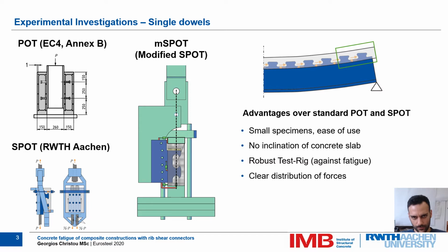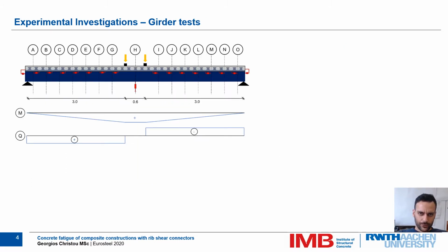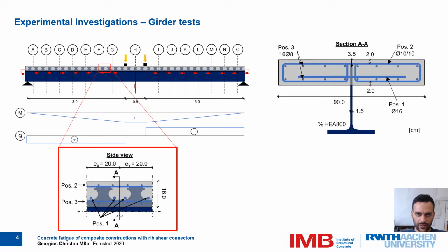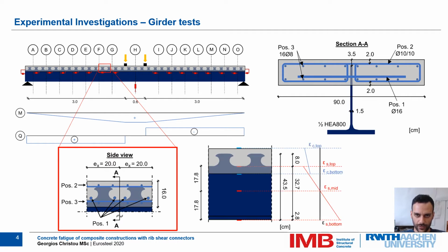Further advantages of the new modified single push-out tests are that our concrete slabs were relatively small and thus we had an ease of use. We had no inclination of the concrete slab as measured by the displacement transmitters, and we have a clear distribution of forces. In addition to the single push-out test, we performed girder tests with a slim girder as seen in the section. The geometry of the dowels and the concrete cover were chosen identical to the ones of the single push-out tests. In our girder test, we measured the slip over the length of the girder as shown by the red inductive displacement transmitters. We measured the deflection and the elongations of the concrete and steel over the height of the girder.